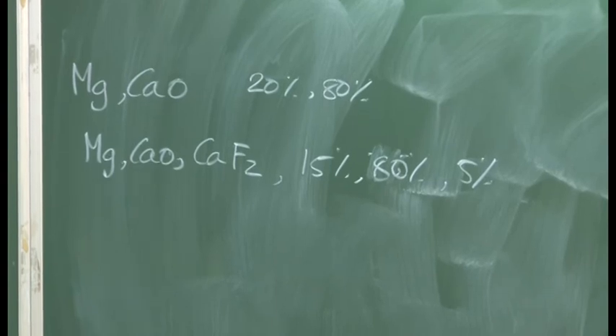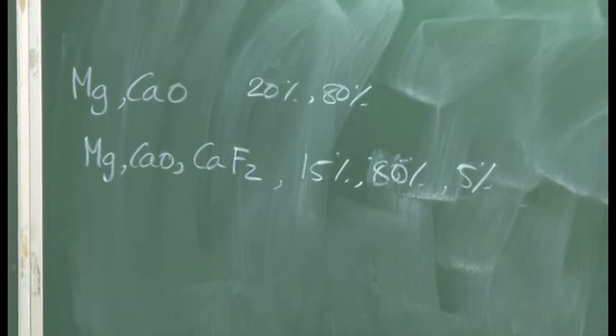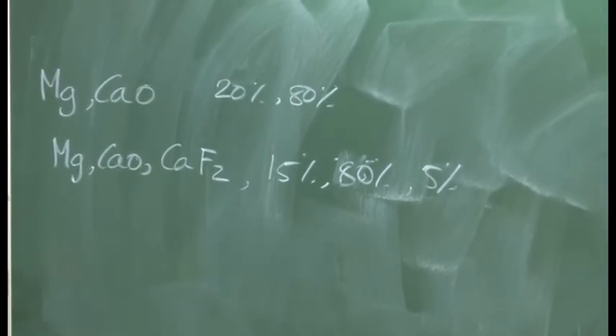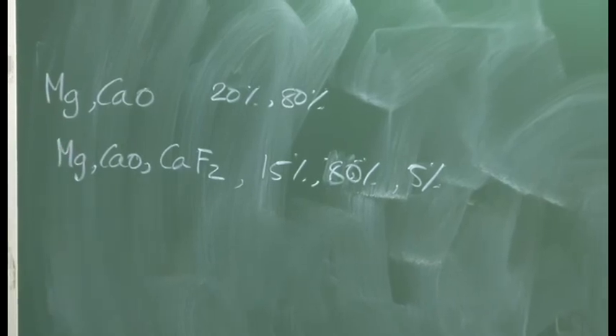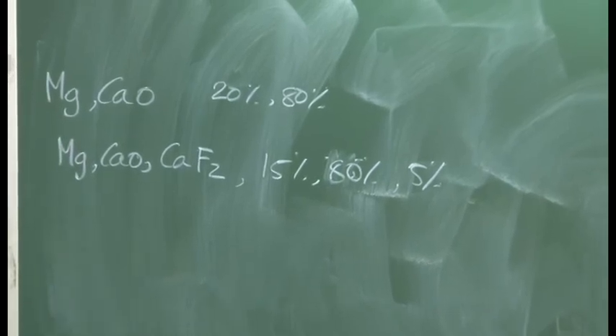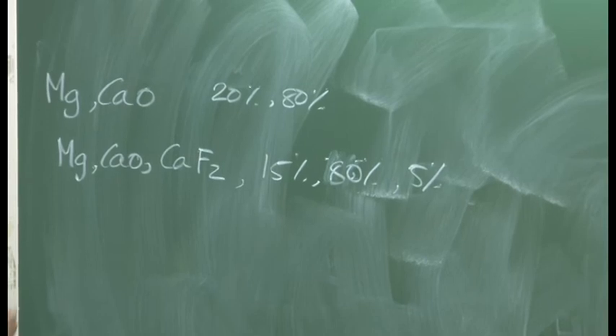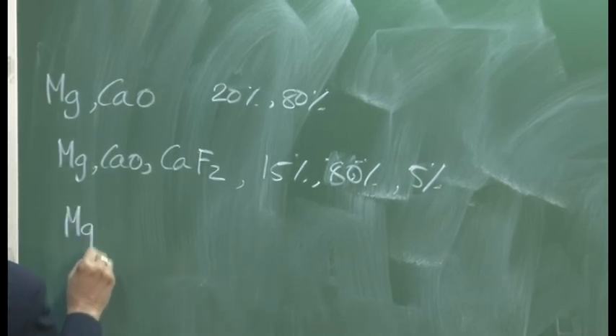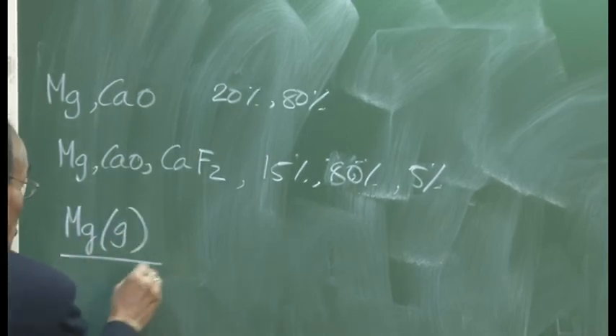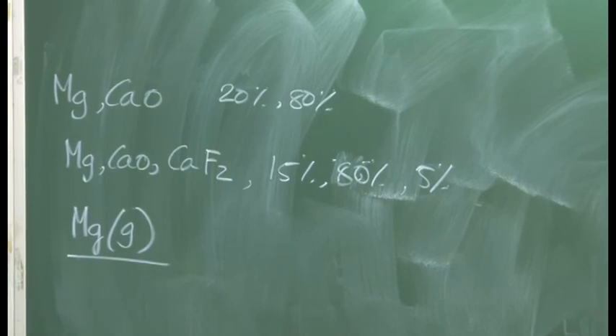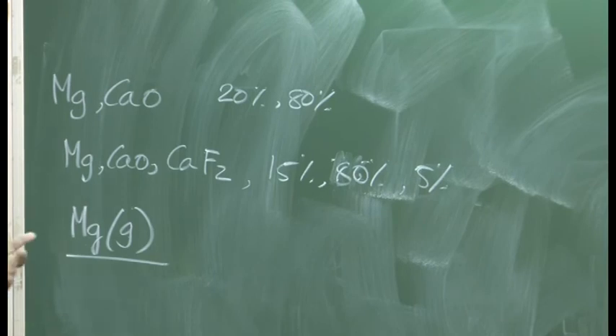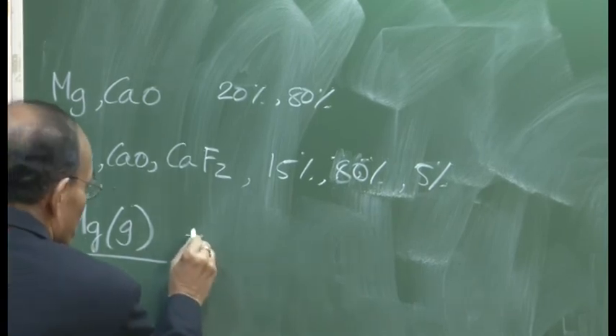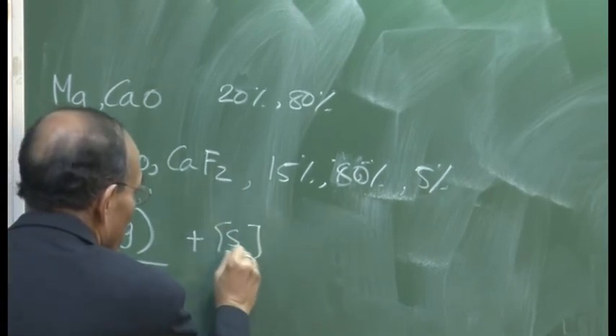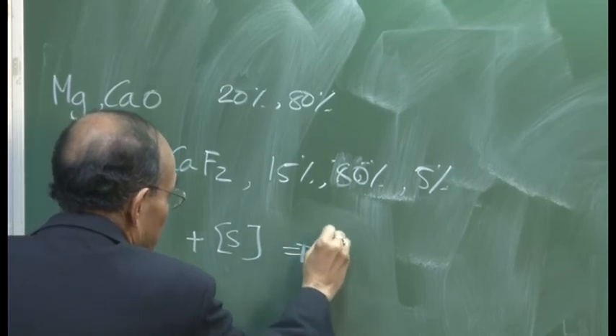desulfurization done, and that desulfurization will take place because magnesium has great affinity towards sulfur. So, magnesium under steelmaking conditions exists as magnesium gas. So, it is going to be a gas metal reaction, and the rate of the reaction could be very, very fast. So, magnesium gas can react with sulfur, which is in dissolved form, to form magnesium sulfide.